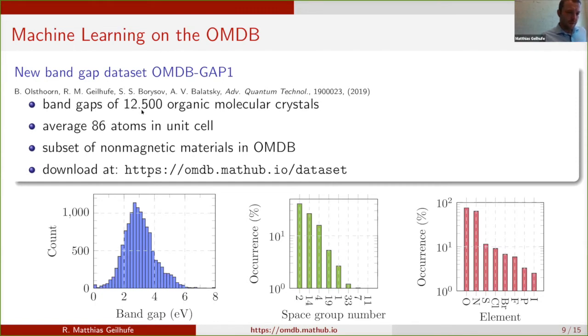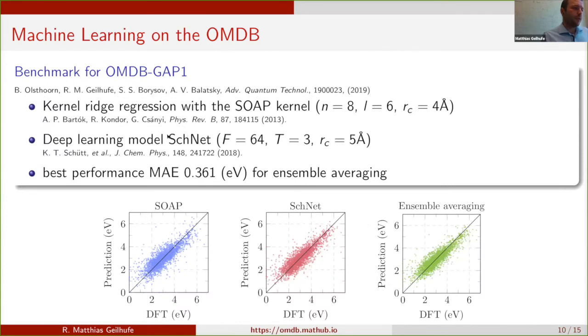What we show is that, applying the standard machine learning methodology which is available right now on this data set, you reach a mean absolute error of 0.36 eV. So if the average band gap of this data set is about 3 eV and your error is about 0.3 eV, then you're wrong by about 10%. It's probably not a rigorous way of defining the accuracy, but it's an intuitive way. And in most cases, this is good enough.